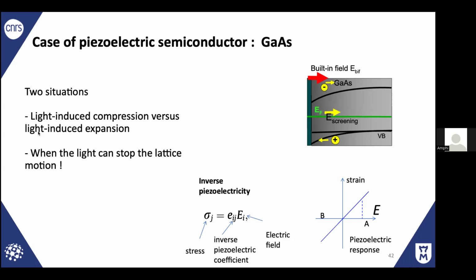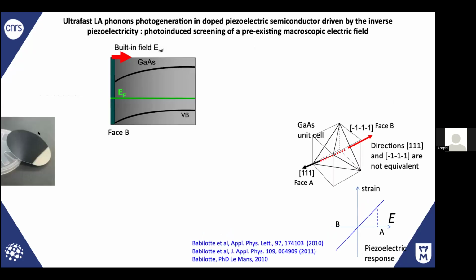In that case, as you know, with the piezoelectric effect, if you modulate the electric field inside, you can have positive strain or negative strain, depending on how you change the electric field. This is a typical sample. You can buy it. It's a 111 direction gallium arsenide, but since it's piezoactive, face B and face A are not equivalent. What does it mean? It means you can induce either compression or expansion of the lattice, depending on the side you shine light. So if you are on face B, when you shine light, this is the typical band structure at thermodynamic equilibrium.